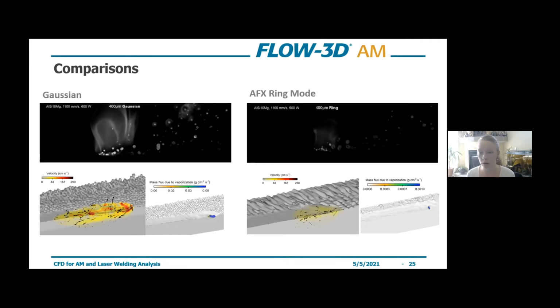just a more quiescent melt pool, less transition stages. And similarly, the mass flux due to vaporization is much lower. So that's going to lead to less spatter, again, lower recoil pressures. And you can see from the experimental images here that the Gaussian distribution did indeed produce quite a bit more spatter than the AFX ring mode.